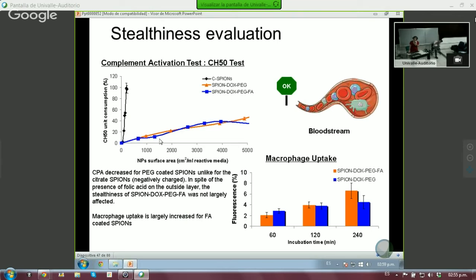And then the red is the SPION with the DOX and the polymer. And then in blue is the SPION with the DOX, with the PEG and the folic acid. And as you can see, the folic acid, if anything, doesn't perturb and doesn't add any significant change, but anyway, it's handy to have it.